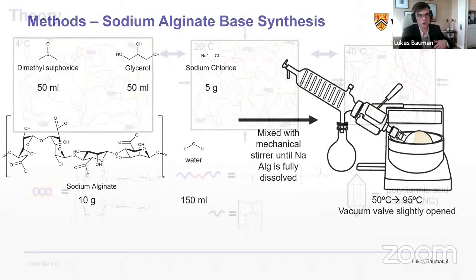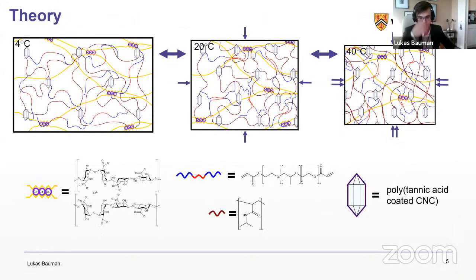And then to this, we add our monomers and then CNCs and the photoinitiator to create our double network hydrogel precursor that's then swollen in calcium chloride to cross-link the sodium alginate networks.